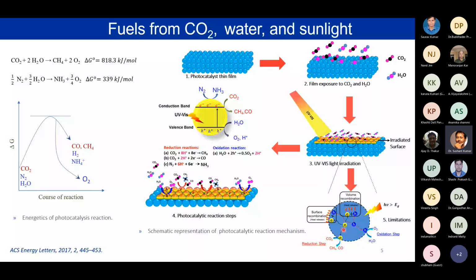And besides that, there is another point: if you have to be selective towards the product, whether carbon dioxide is going to CO, or carbon dioxide is giving methane, you have to have those potentials. And those potentials are governed by thermodynamics, because thermodynamics tells you whether those kinds of products are possible or not. And that thermodynamics comes from the kind of semiconductor or photocatalyst that you have prepared. So the band positions, the conduction band position and the valence band position, are going to govern whether it is feasible for the CO2 to convert to CO or methane or some other product.